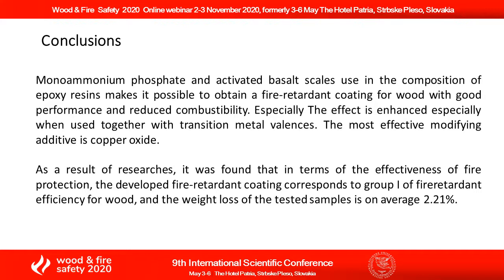As a result of researches, it was found that in terms of the effectiveness of fire protection, the developed fire retardant coating corresponds to Group 1 of fire retardant efficiency for wood, and the weight loss of the tested samples is on average 2.21%.